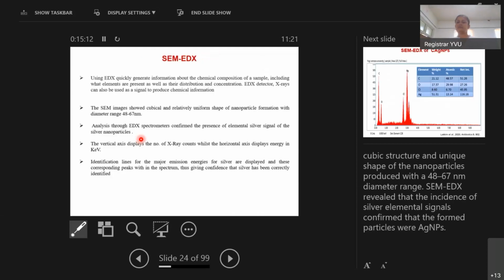After that, the elements present in the green synthesized silver nanoparticles were analyzed by EDAX. Using EDAX, we can quickly generate information about the chemical composition of a sample, including what elements are present as well as their distribution and concentration. The EDX detector and X-rays can also be used as a signal to produce the chemical information. The images showed cubical and relatively uniform nanoparticle formation with a diameter range of 48 to 67 nm. The vertical axis displays the number of X-ray counts, while the horizontal axis displays the energy in kiloelectron volts.